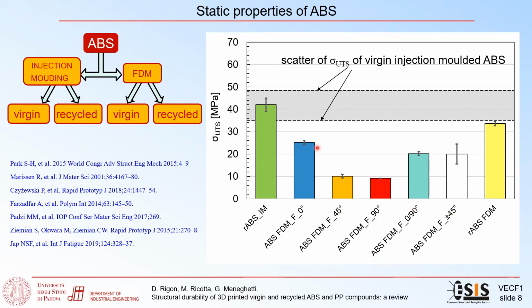The best performance with this technology was obtained with the 0-degree orientation of the raster, and the lowest was obtained with the 90-degree orientation. The last bar is related to the recycled ABS produced by FDM. The UTS of this material is surprisingly close to the reference virgin injection molded ABS. However, no information about the process parameters used to produce this material was reported in the paper.